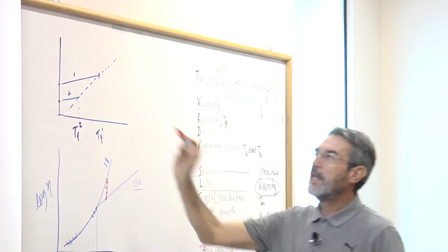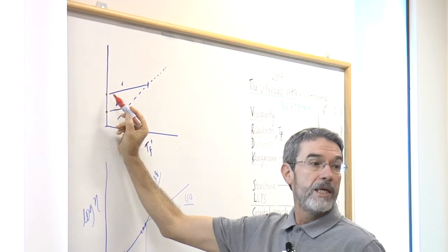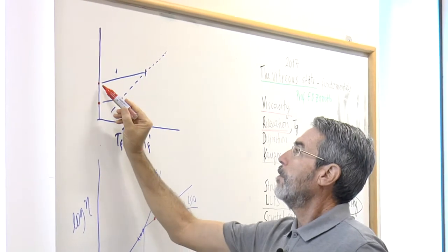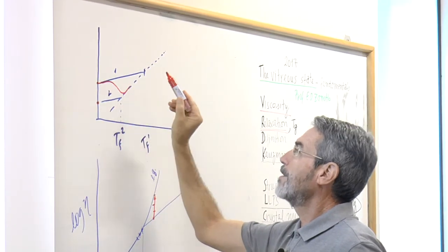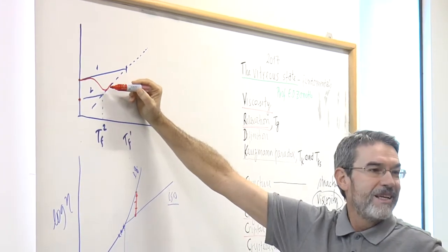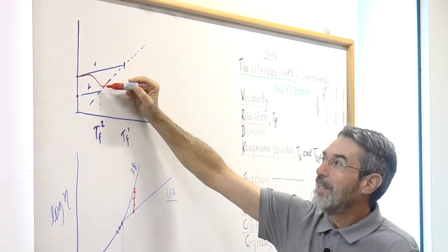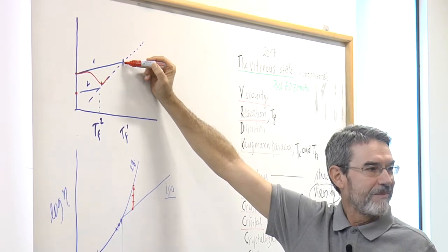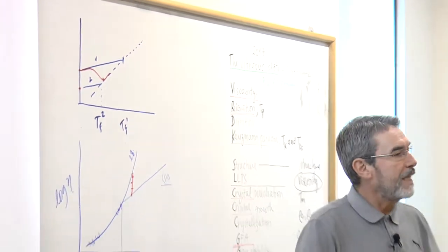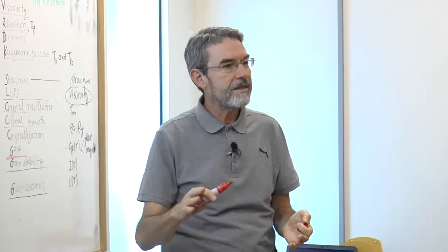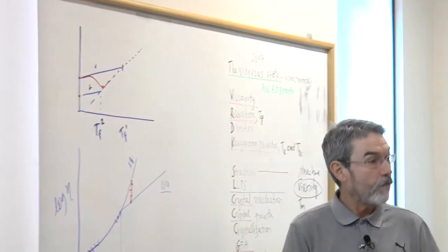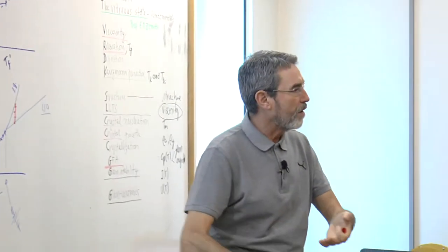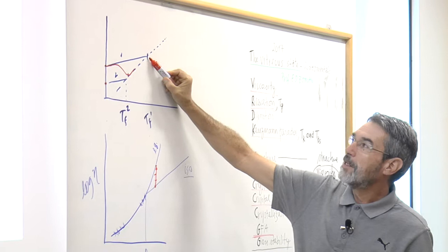Now what happens if I take this glass here and heat it up in a DSC or in a dilatometer? It will go, and will relax. This is the Tg. The Tg of this glass is much lower than the fictive temperature of this glass, because it comes to that range of 10 to the 12 pascals second, and then we relax back to this point, and that's the Tg that we measure. Tg is something that we measure. It depends also on how fast or how slow we measure, but it's not the same as TF.